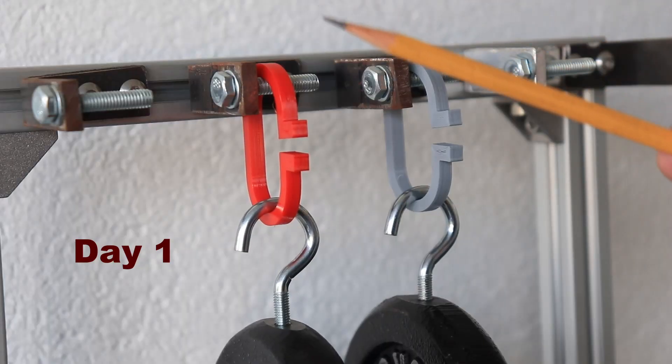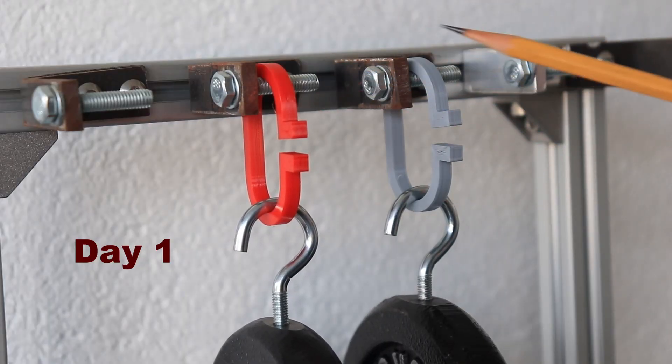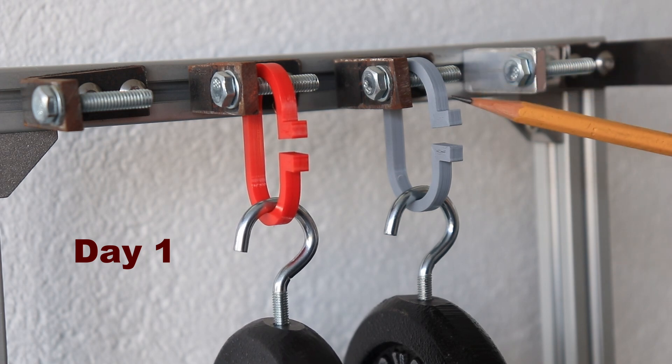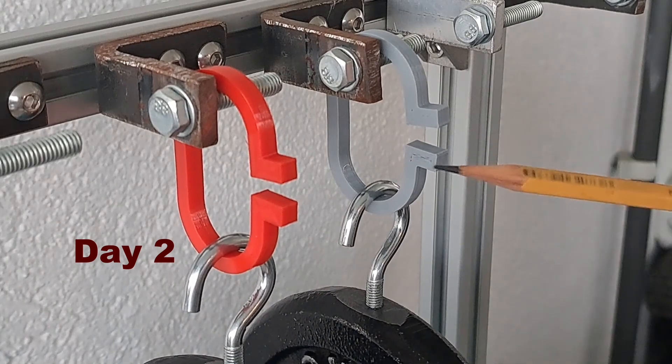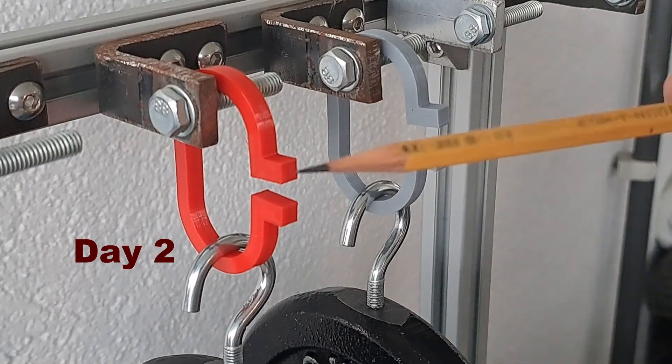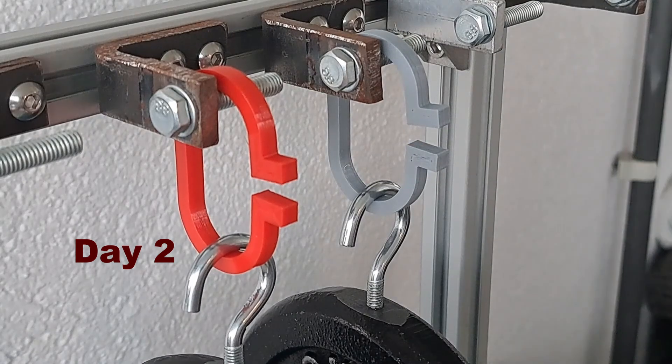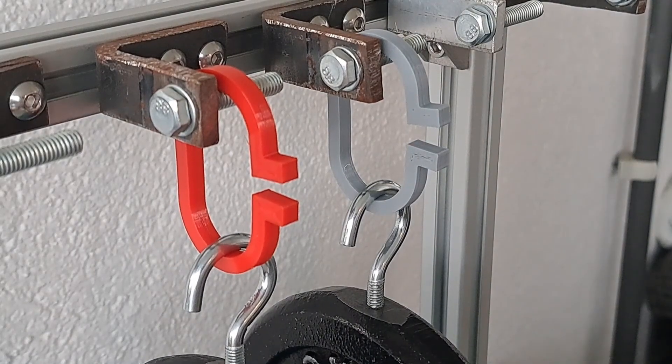After 1 day, very minimal creeping on the regular PLA and more than 1mm of deformation on PLA Strongman. Day 2, I already measured them. Still approximately 0.5mm of creeping here and maybe 0.3 here, but nothing visually interesting, so let's jump in time.